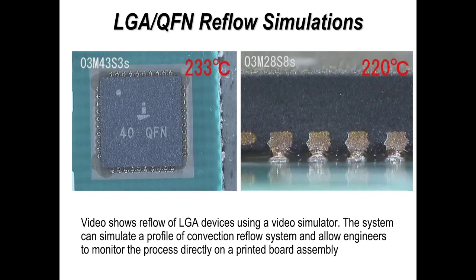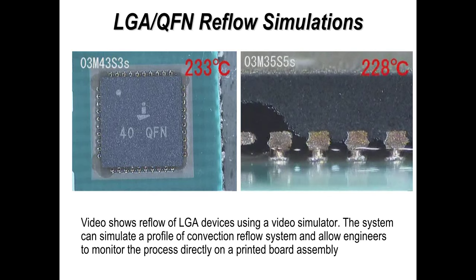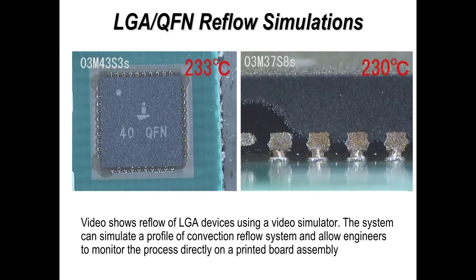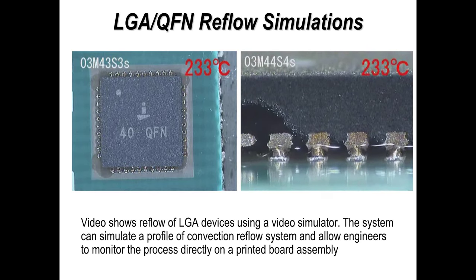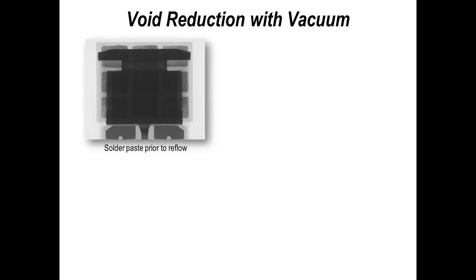And we can see a certain amount of component float or movement. So there's a lot of volatile material present. And really, that's what you're trying to remove, which is present within the bulk of the solder. If you can reduce the amount of volatile material from the solder paste by going to lower residues, that's good. But you mustn't affect the quality of the process by doing that. But using vacuum does give you the ability to reduce void formation.